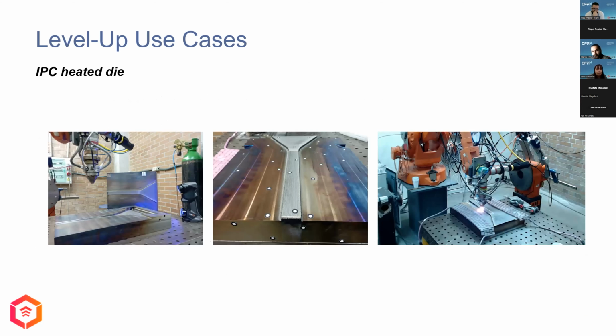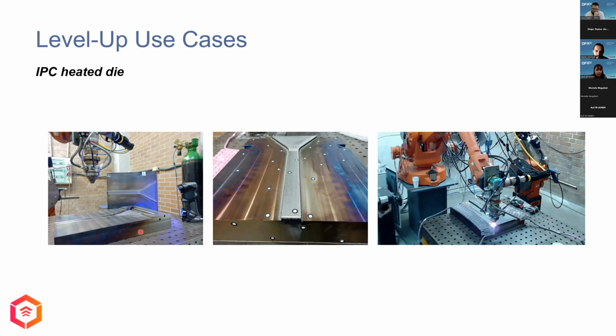So we replaced the cobalt alloy with an Inconel, and also we used a preheating system here to 250 degrees. And also you can see the progress of the manufacturing. And here the results of the surfaces with the coatings.